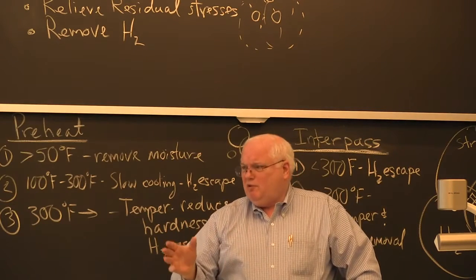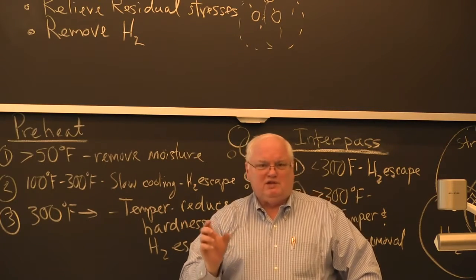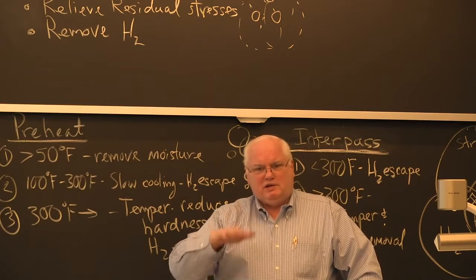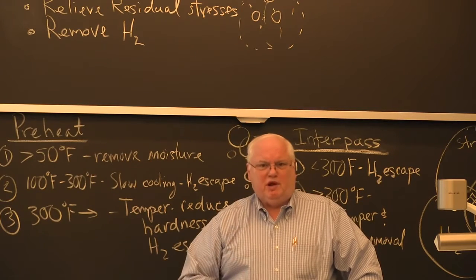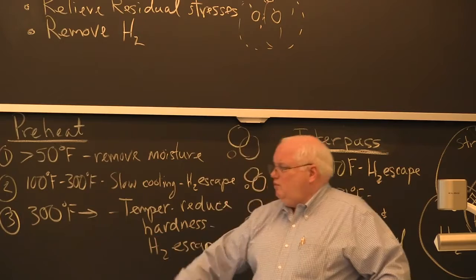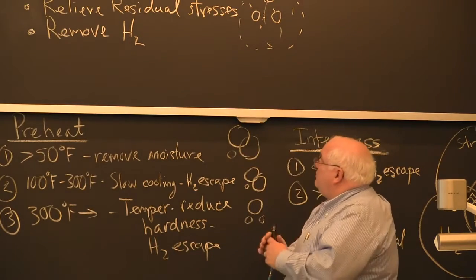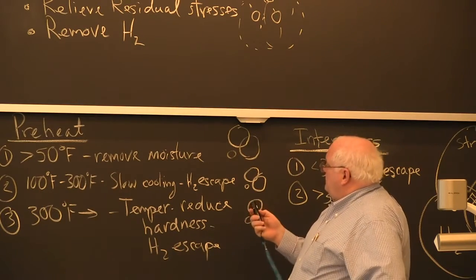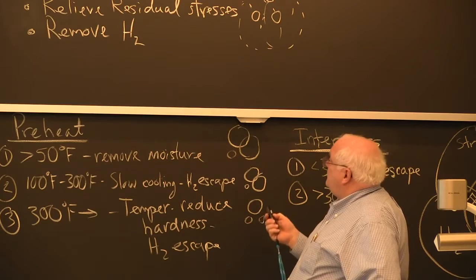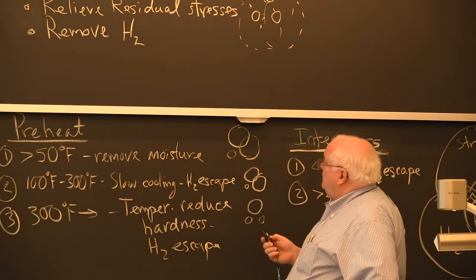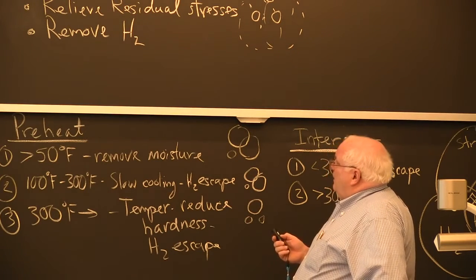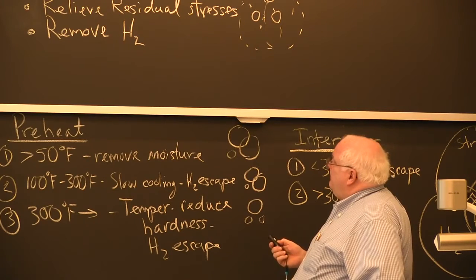Nowadays, they have little computer programs that will tell you exactly how long it takes to get the inside up to a reasonable temperature. But in the old days, one rule of thumb you'll often hear is 1 hour per inch of thickness. But that only applies in the couple of inches thickness range. Above that, you actually can do it a little quicker.